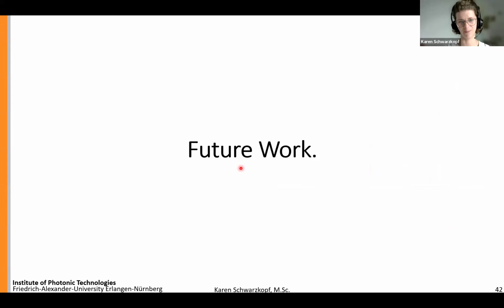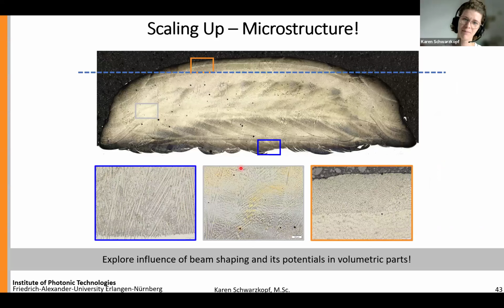As I already mentioned, this case study was relying on single track experiments. And so the next step would be to really scale up, meaning heading to volumetric build-ups, for instance, as shown here. One approach would be to focus on the microstructure adjustment. First ideas can already be shown here, where we could see a laminar structure in the center and also the bottom, where one defined beam shape was applied, whereas on the top of the volumetric build-up, a different beam shape was applied and a change in microstructure, namely towards equiaxed grains, was observed.